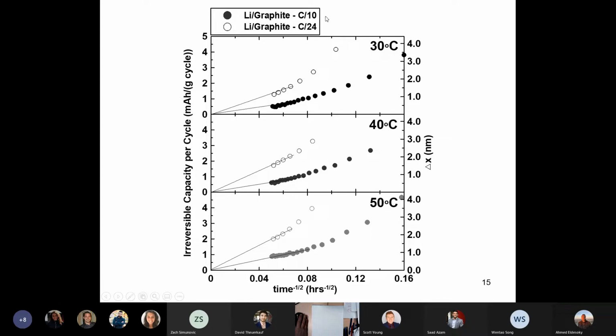So what we did was we measured experiments where lithium graphite cells were charged and discharged with a 10-hour charge and a 10-hour discharge, that's C over 10, or a 24-hour charge and a 24-hour discharge, that's C over 24, at 3 different temperatures, 30 degrees, 40 degrees, and 50 degrees C. And we plotted the irreversible capacity per cycle versus T to the minus a half for these experiments. So the early cycles are shown on the right-hand side, and then as time progresses, you move to the left. And these solid lines are guides to the eye, because if this data follows the T to the minus half law, it should be a straight line. And it looks like these data are coming into sort of straight line behavior.